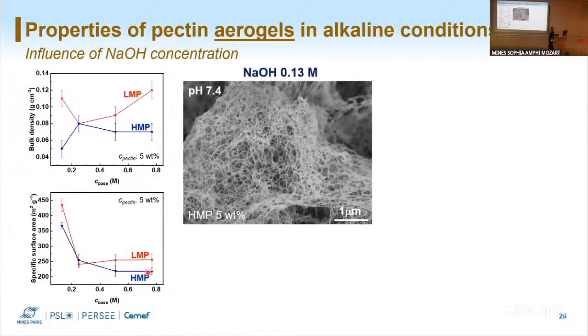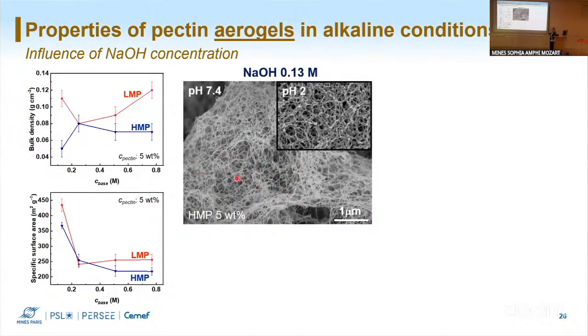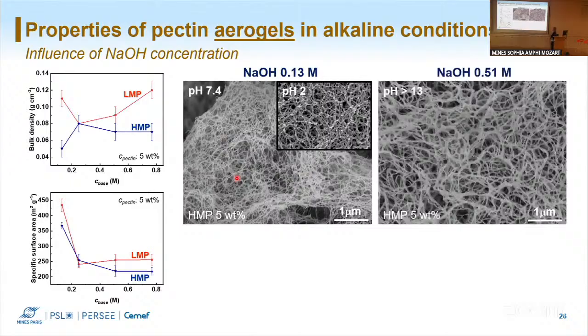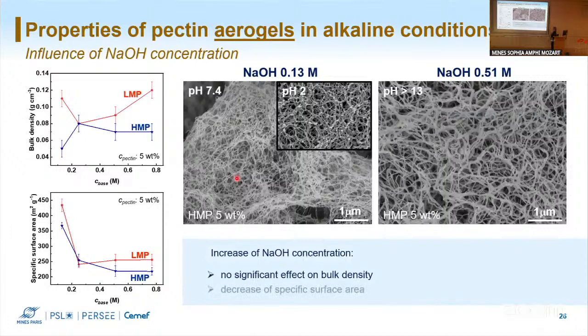We can see these properties depicted on the images of our structure from scanning electron microscopy. So here we are in the low concentration of base, so in the very beginning. We see we have small pores and a very fine structure, and here we see the structure at acidic conditions. So if you put one on top of the other, you'll see that they are very, very close. But then when we go to higher pH, more base in our system, we see that the structure changes. We have thicker fibrils in our network, and the pores start to be bigger. So for the aerogel materials dried with supercritical drying, when we increased the concentration of base, we didn't have a real effect on bulk density, but then we had a huge decrease of specific surface area, as we can see also from the structure.